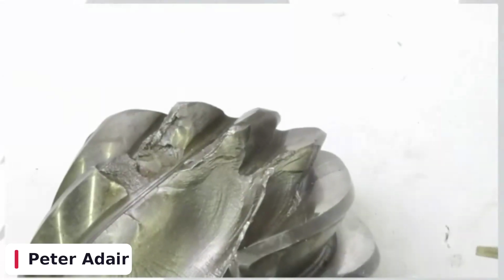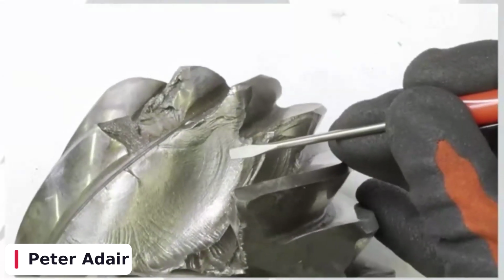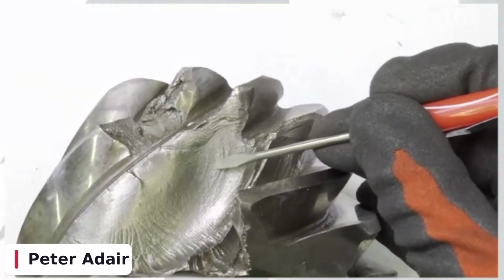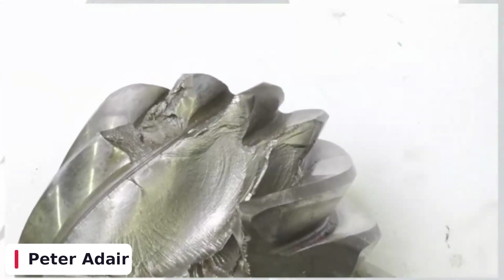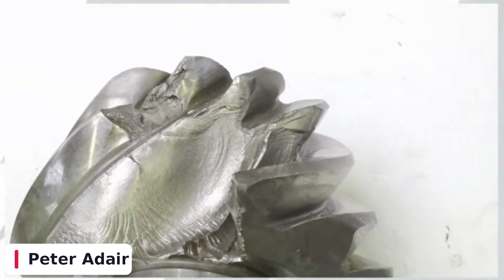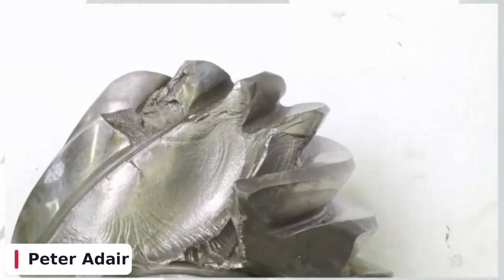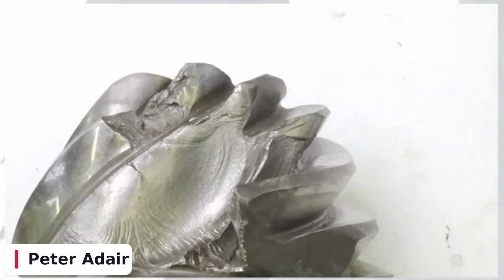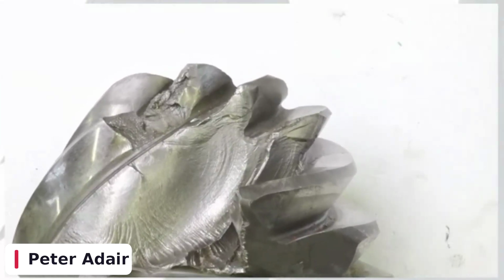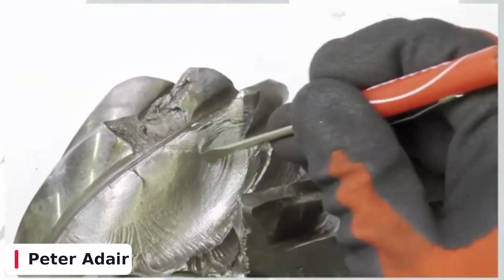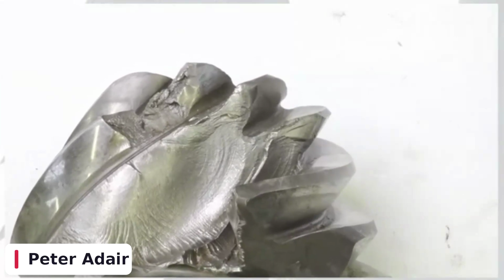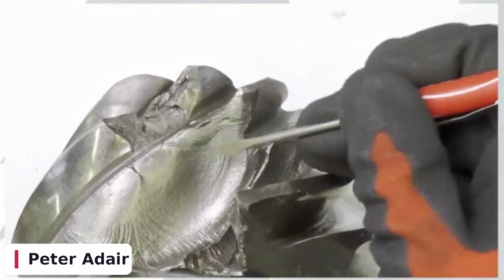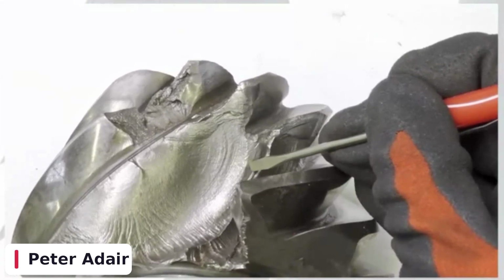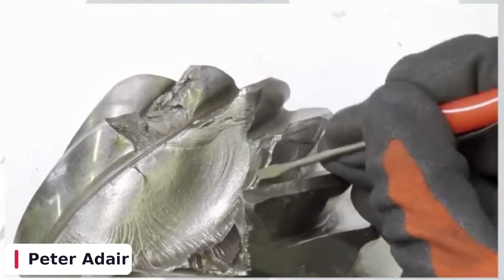So when we go back to the part, we can see a number of cycles through here. So this thing had overload, but it made it through a number of cycles. So the overload was there, but it was not as severe as you would think. It's not an 80,000 pound overload. It's probably more like a 10 or 15,000 pound overload. And he did that many trips with it, or tried it that many times. So each time they initiated a crack.